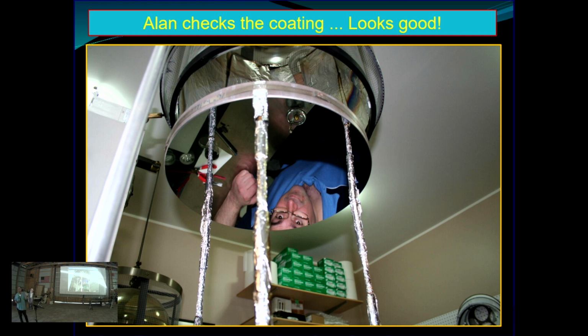But what you're looking for is looking at this. You're looking at the mirror at a very shallow angle, and you see it change colors on you depending on the thickness. So with magnesium fluoride, it'll start turning yellow, and then it'll go magenta. At that point, I stop it. That tells me I got a quarter wave on. Then I start the cerium dioxide coating. Then it's going to go from magenta, then it's going to go green. And then I wait for the green to disappear back to white, and I stop it. At that point, I'm done.